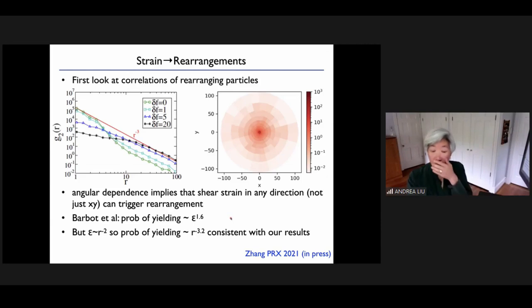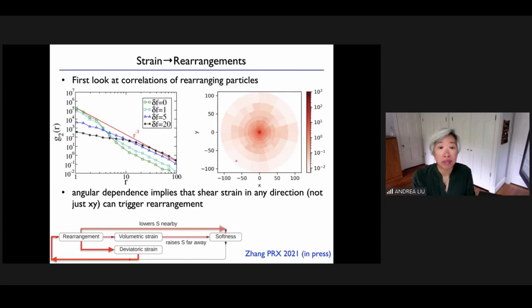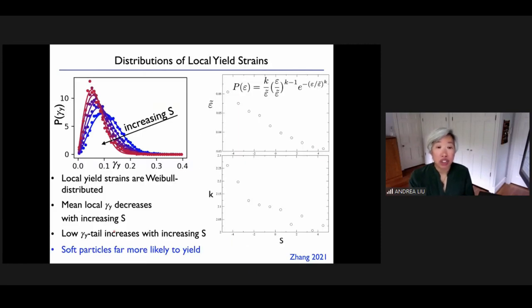Well, the idea is that there is actually a distribution of yield strains which has a low tail, which is a power law, and the strain scales like 1 over distance squared, so the probability of yielding should go like 1 over r to the 3.2, which is very consistent with what we have. Okay, so that's that piece. The rearrangement can give rise to deviatoric strain, okay, which can cause more rearrangements. All right, but the yield strain has something to do with it. So what is the yield strain distribution?